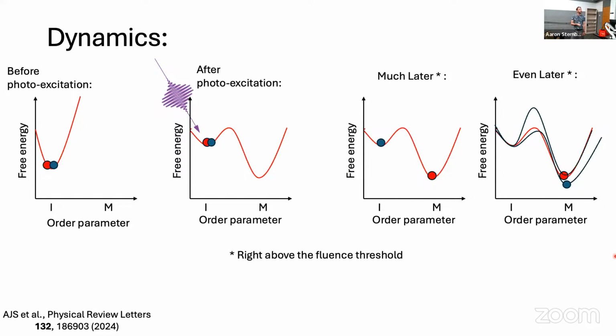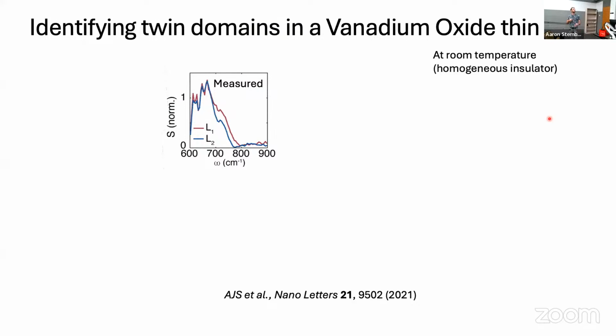likely because there is some change in the free energy surface, whether that's a change in the bulk energy, a change in the energy barrier separating these two phases, or some combination of the two effects. However, we can't really say. And so this tells us some qualitative information, but it doesn't really tell us what's going on, what is causing the system to be inhomogeneous, and what is actually inhomogeneous. In order to address that, we took a look at several things.